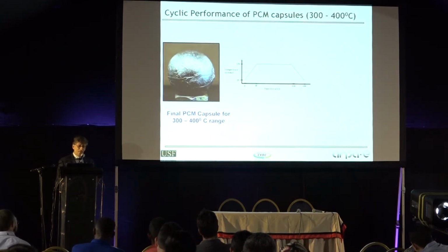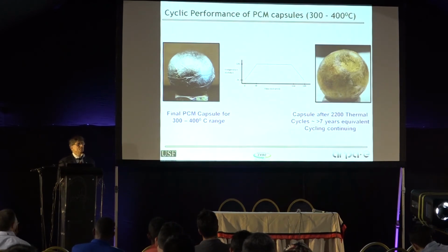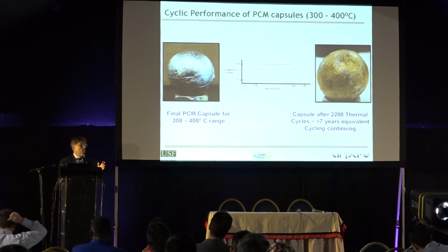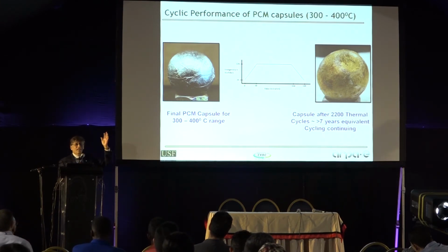Okay. So now we had these capsules that work up to that temperature. We looked at their cyclic performance, and we did performance for up to about 7 years. And in 7 years, no properties changed. The capsules did not leak, the capsules did not break. So we felt that these capsules would work for as long as that solar power plant will work.